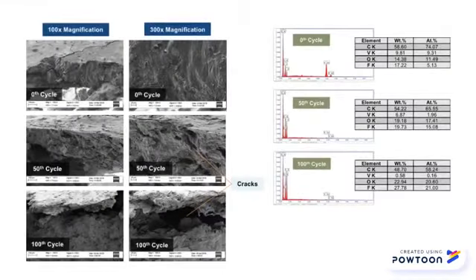From the EDX result, the weight percentage of the vanadate decreased from 0 cycle to 100 cycles. This is due to the dissolution of vanadium. Besides, fluoride became higher with longer cycle number. The F formed on the surface came from the side reaction of the PTFE binder.